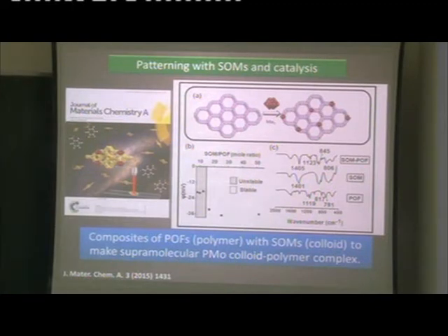This charge has a distribution from the surface of the colloidal particle, which usually follows the Poisson-Boltzmann distribution. That means you have an exponential kind of decay of the charge from the surface of the colloidal particle, and then you have the stabilization.